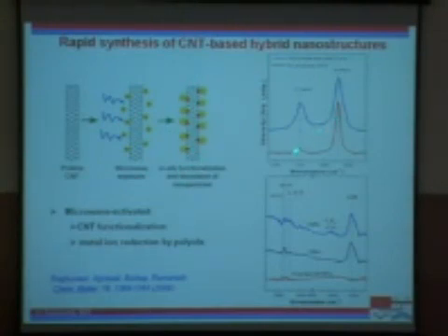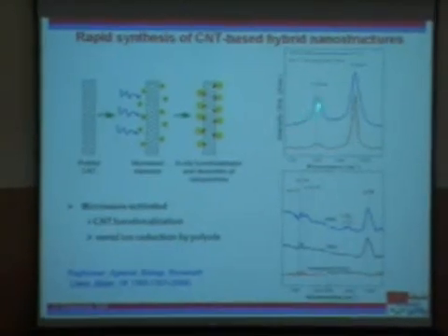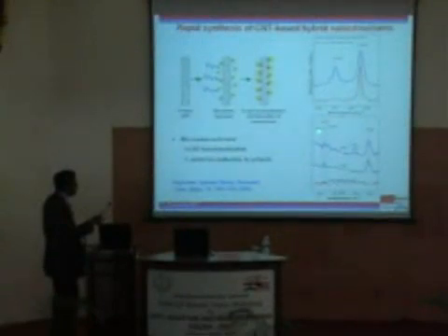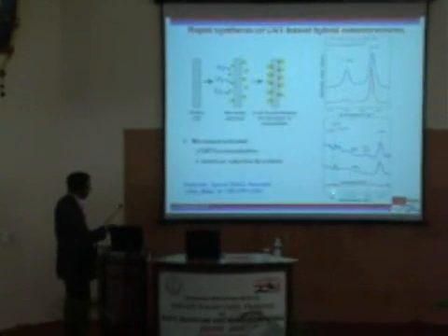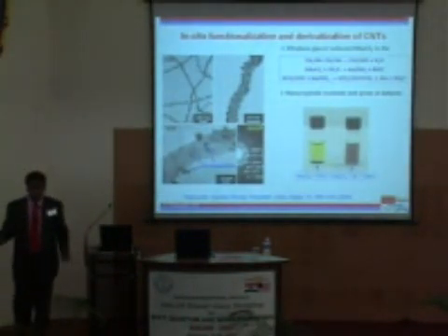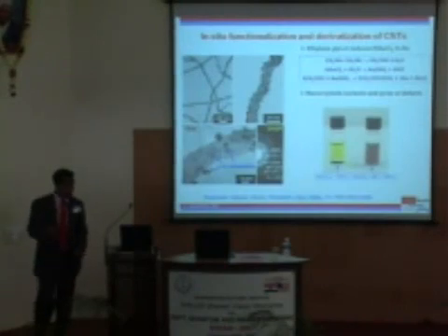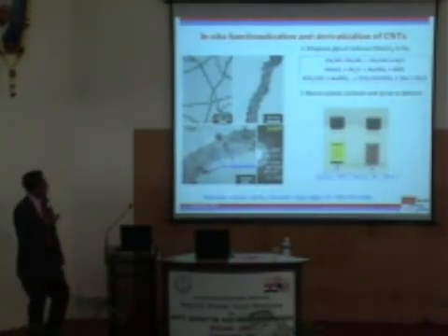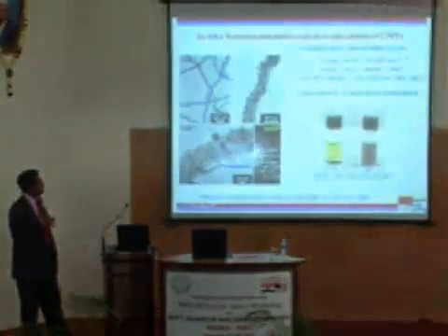You can see over here, you're creating defects. The D band goes up, so defects are created. And in addition, you're seeing that the C=C, the alkyl bonds and carboxyl bonds are evolving as you increase the microwave exposure. The beauty is that all this happens in a minute or 2. You just take nanotubes, put in the metal salt solution, put it in a simple microwave, turn it on. This is what happens. If you were to do this by conventional routes, it'll take you about a day, and also you'll be destroying the tubes and their properties.